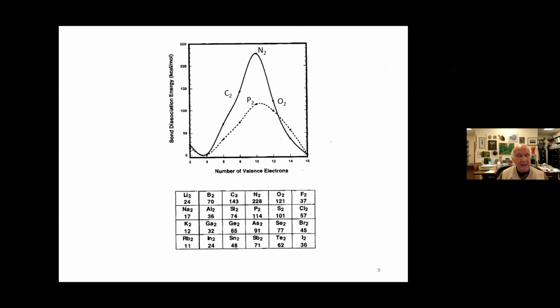They are also there. Another way that chemists see this, or at least theoretical chemists who really have a lot to learn in this business because they're particularly naive about chemical stability. Here is a homonuclear diatomic, so the first row and second row. The most stable diatomic to atomization is the nitrogen molecule. It takes 10 eV to knock apart a nitrogen molecule into 2 nitrogen atoms. The next most stable one is C2, the next one O2, the next one, P2 in the second row. Here are 4 molecules, each of which takes more than 4 eV, around 5 eV or more, that's the energy you'd need to put in to break them apart into atoms.